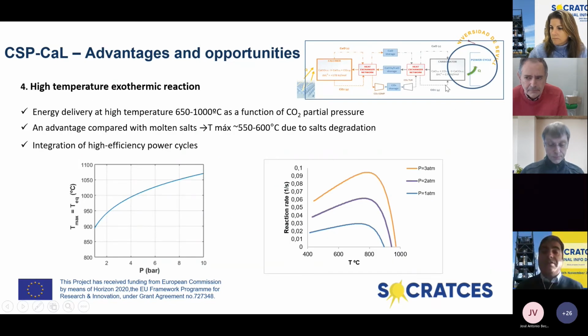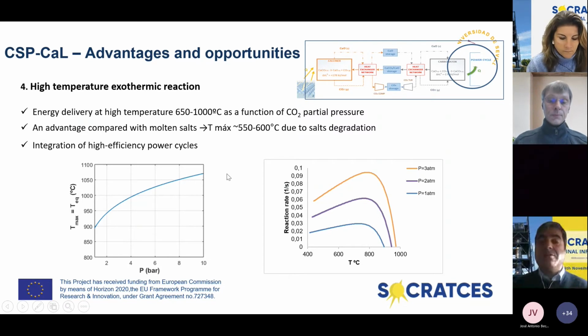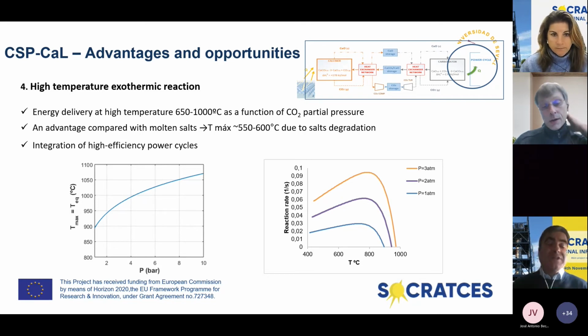On the side of the discharge, we have heat release. Depending on the pressure in the carbonator, we can have very high delivery temperature that allows the integration of advanced power systems like supercritical carbon dioxide cycles, and even higher temperatures, even gas turbines. The behavior of the carbonation will depend on the temperature in the reactor. Here you see the reaction rate depending on the pressure and how it changes clearly depending on the carbonator temperature. This is an important issue that affects the design. It will be highlighted later on in this webinar.